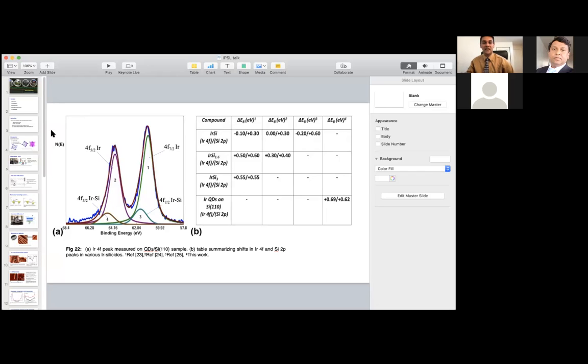The other two surfaces, silicon 111 and silicon 001, have 4-fold symmetry. So we will not get the same direction. If we form any nanostructures, we might get random directions. So that is the main purpose. We use the silicon 110 surface because it shows high anisotropy. Thank you.